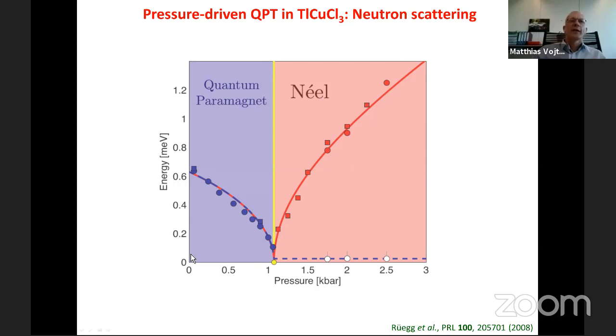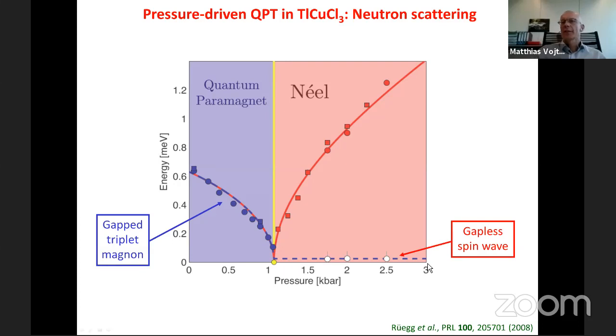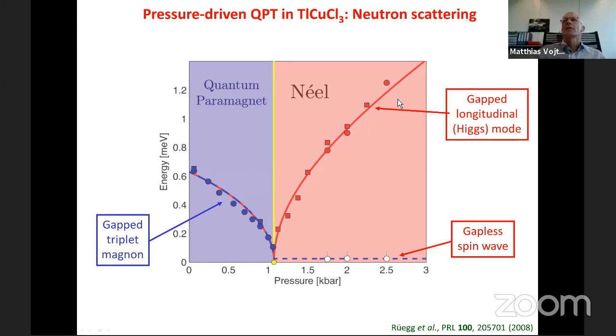So there is the minimum energy of the excitations, minimum in the sense as function of wave vector, as function of applied pressure. And what you can see is that on the paramagnetic side, you see the energy of this triplet magnon or triplon, which is finite and then goes to 0 at a particular point. And then there are spin waves, which are essentially gapless. They have a small gap because there are anisotropy terms. Otherwise, they would be gapless because of Goldstone's theorem. And in addition, there is a novel mode, which is a so-called longitudinal excitation mode, which some people also like to call Higgs mode, which has a finite energy and also vanishes at this critical point. So in other words, this system here is a very nice realization of this paradigm of magnetic quantum phase transitions.